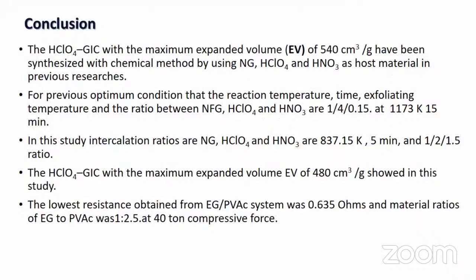In conclusion, in the first slides I didn't go through the concentrations and the weight ratios of the chemicals we used in the reactions. We used HClO4 acid and also nitric acid for this research. We take natural flake graphite, HClO4 and nitric acid in the ratio 1:4 and 0.15, and the temperature is 1173 kelvin for 15 minutes for the exfoliation process. There are several past studies on exfoliation using acids, but in our system these are the optimum ratios.